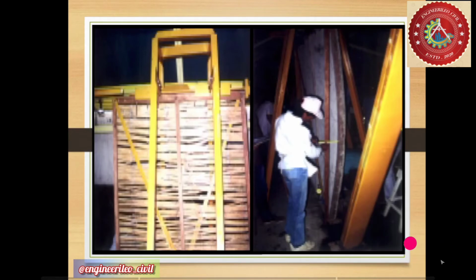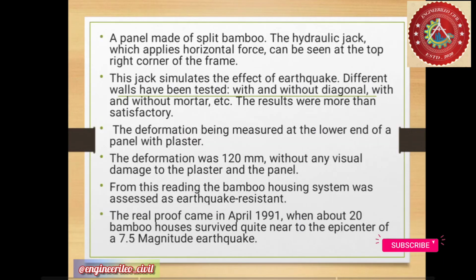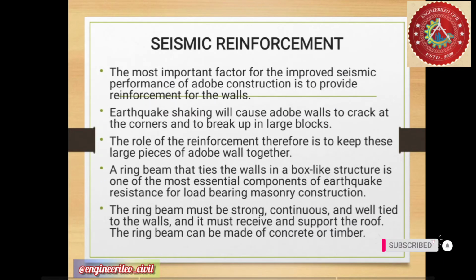The deformation was measured at the lower end of a panel with plaster. The deformation was 120 mm without any visual damage to the plaster panel. From this reading, the bamboo housing system was assessed for earthquake resistance. The real proof came in April 1991 when about 20 bamboo houses survived quite near a 7.5 magnitude earthquake. Now we'll study about seismic reinforcement.